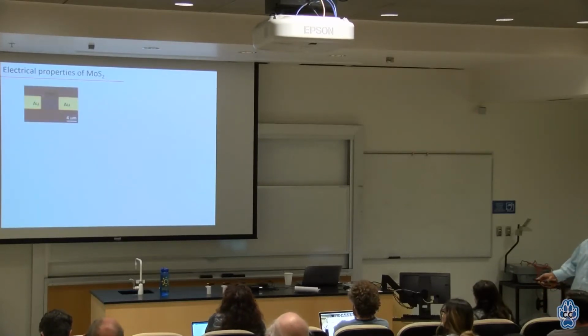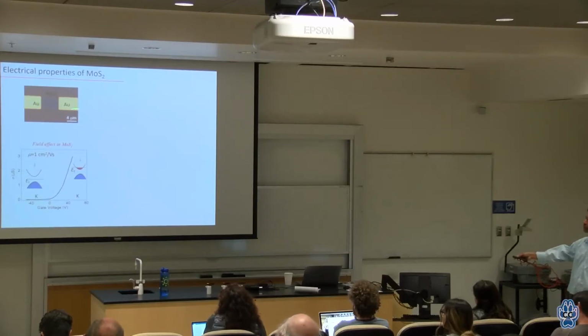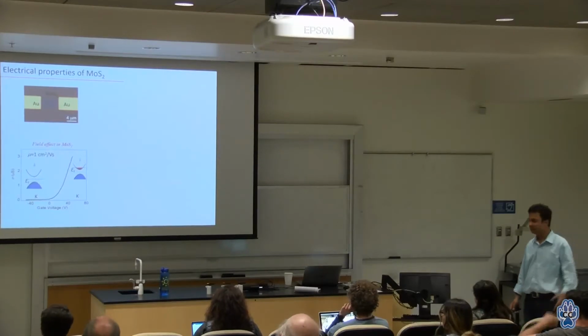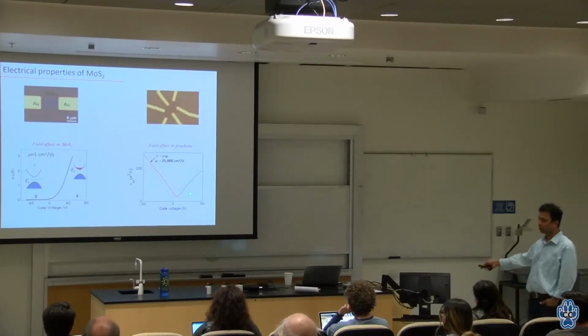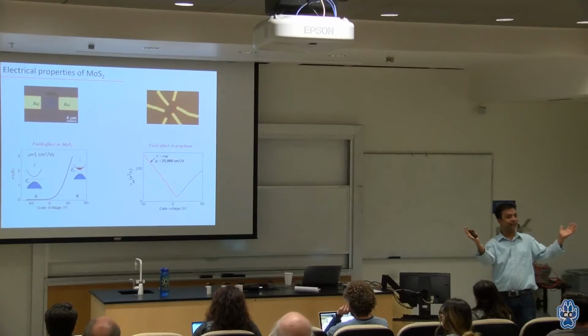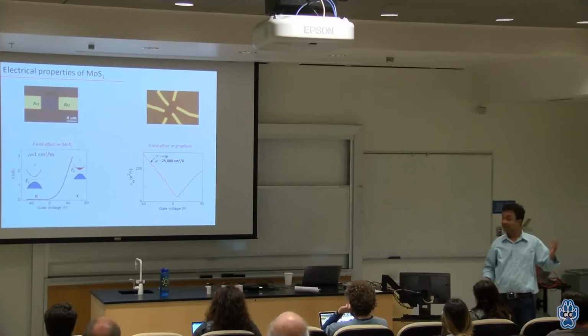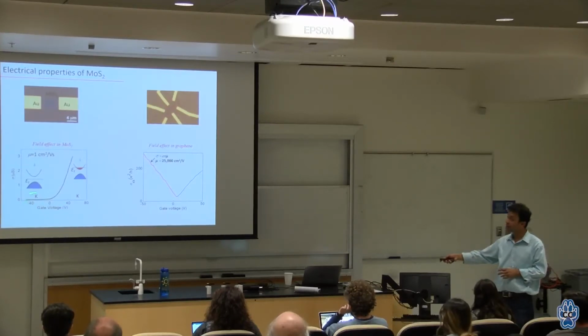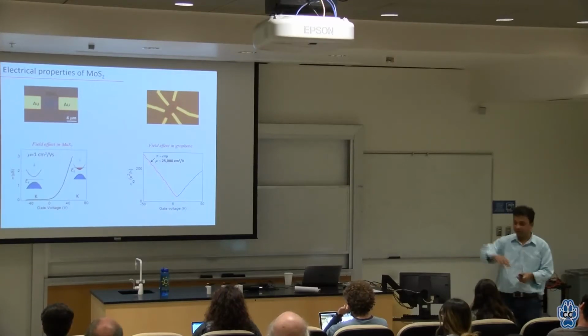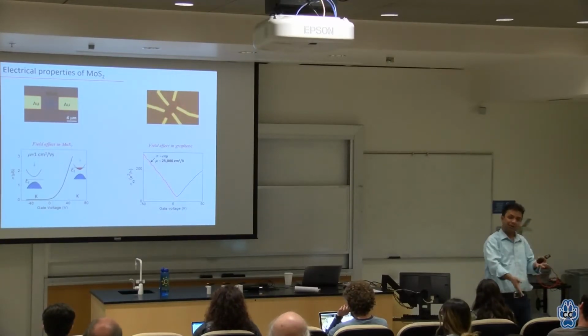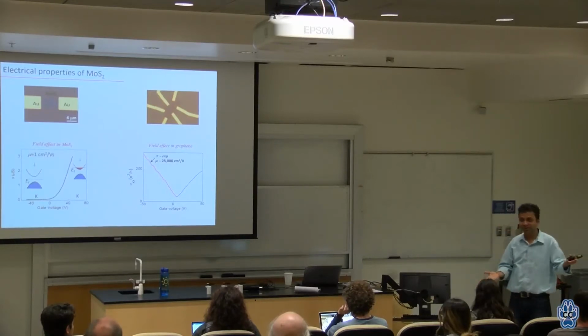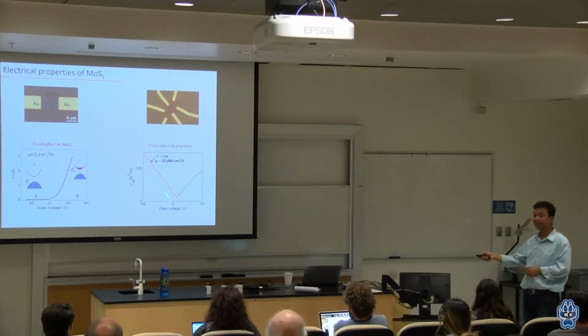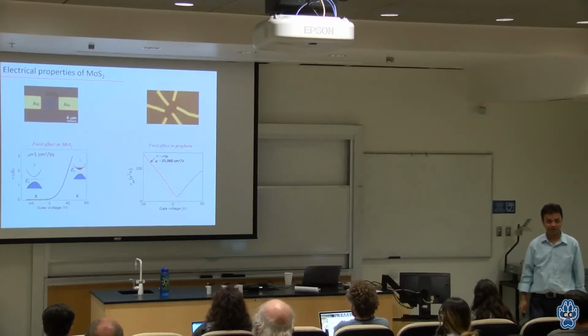So the electrical properties here is your MoS2 connected by 2 gold electrodes, and this is a very transistor-like behavior, very similar to your silicon. And then, as you have already discussed, graphene looks very different, right? So what is the problem of graphene? Graphene does not work as a switch. Here you can completely turn it off. Here you cannot turn it off. You change the voltage, so you change the faucet this way, water flows, go other way, water flows. So you cannot make a transistor out of graphene, but you can make a transistor out of MoS2.